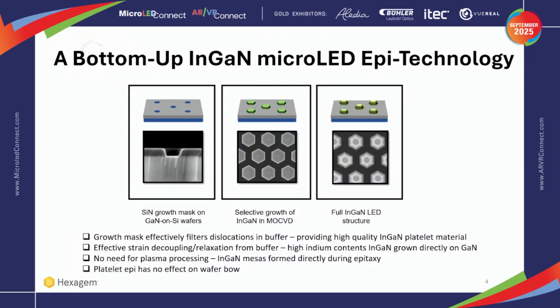On these truncated pyramids, we grow the full LED structure. So each individual platelet is a fully working LED. The difference between the colors is, of course, the quantum well. So red, blue, or green we can do in the same material system. There's also no need for plasma processing. So out of the epi, we limit the growth, so we don't grow these platelets together to form a film. They are separated out of the epi. And since we don't form a closed film, we don't add any extra strain, so we don't add to any bow issues. So whatever bow you have in the beginning in the GaN buffer, this is what you have after the epi growth.